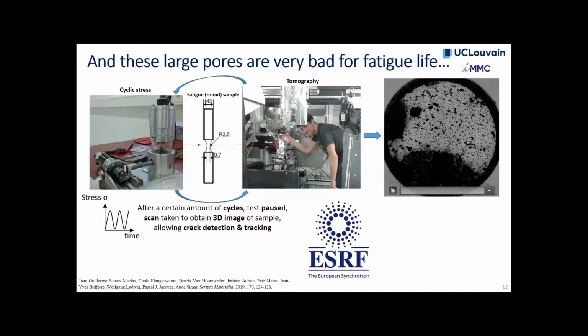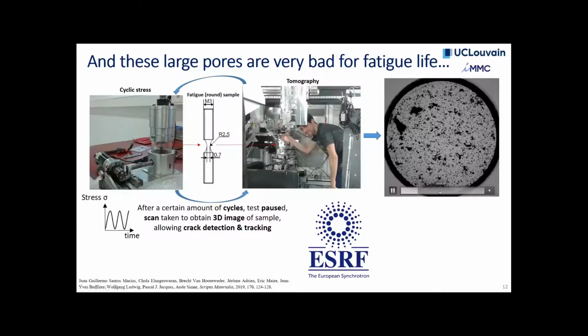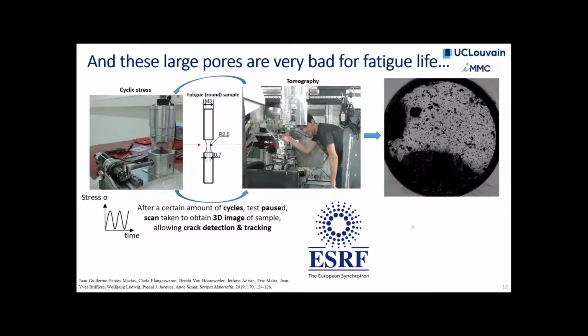And he's been able to identify that the origin of this fatigue crack is actually on a really large porosity. And you can see some of them here. It's impressive the amount of porosities that you have here, but this is just due to the fact that it's a projection, so we're projecting all the images on one slice to have a 2D look. So you're really seeing that these fatigue cracks are definitely initiating on these large porosities. So we need to do something about these large porosities, and that's the second message.